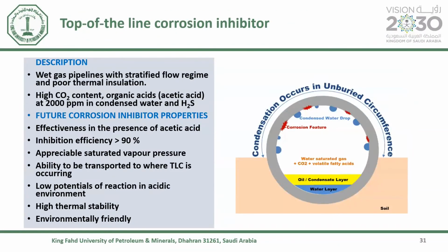So top of the line corrosion inhibitor, how do we develop a corrosion inhibitor that can be effective in the presence of acetic acid and can protect the upper part of the pipe, efficiency of like 90%. And this kind of model have appreciable vapor pressure because you need to vaporize and then protect the top of the pipe. So this is one of the conditions, and also it must have very high thermal stability also.